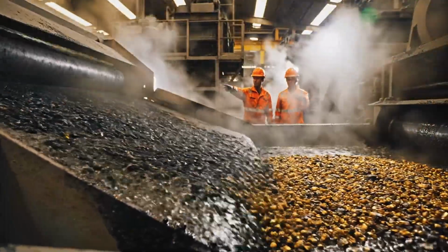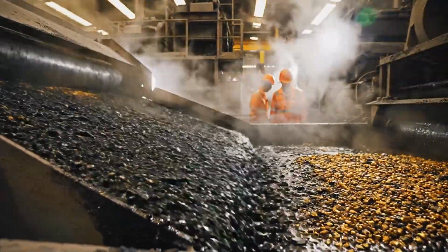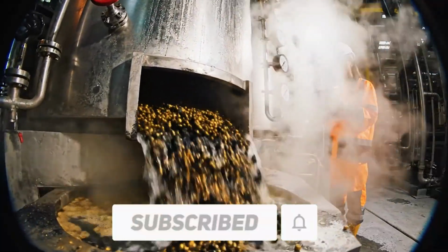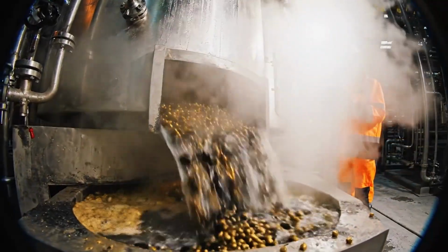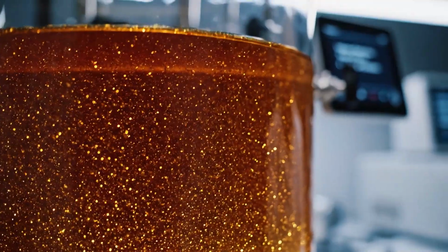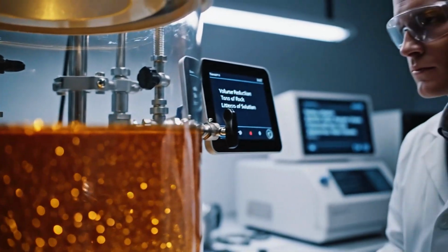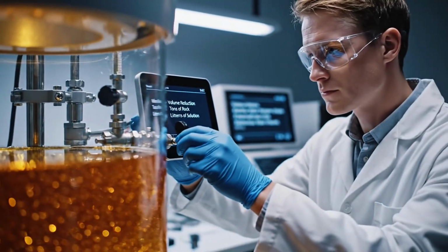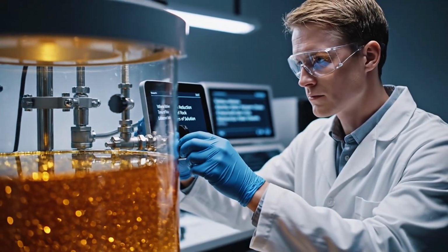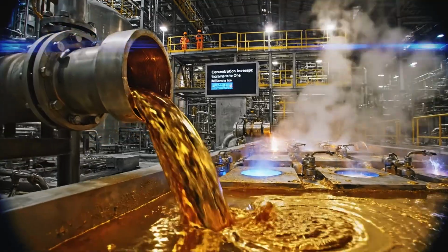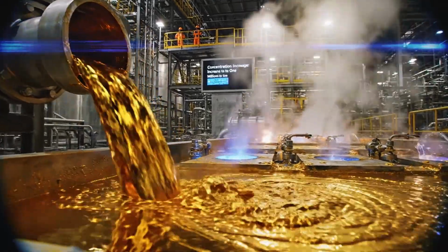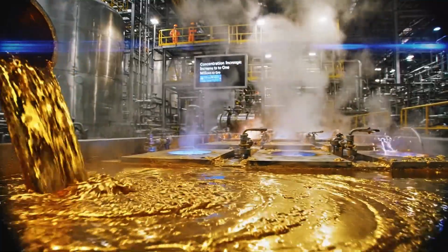The gold-loaded carbon is separated from the slurry and washed with hot caustic solution that strips the gold back into liquid form, creating an extremely concentrated gold solution. At this stage, what started as tons of rock has been reduced to just a few hundred liters of liquid containing several kilograms of gold, a concentration increase of millions to 1.